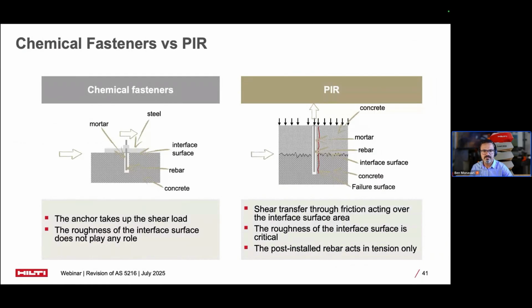Post-install rebar, on the other hand, connects two concrete members, existing and new construction. Shear forces transfer through friction over the interface surface area, making interface roughness critical. The post-install rebar acts primarily in tension, connecting the concrete section rather than supporting an attached fixture. This fundamental difference requires different design approaches and failure mode considerations.